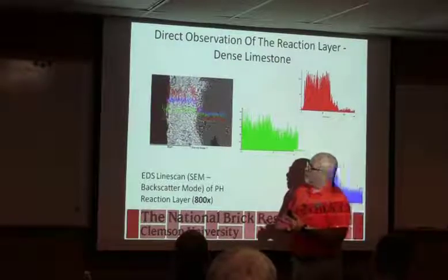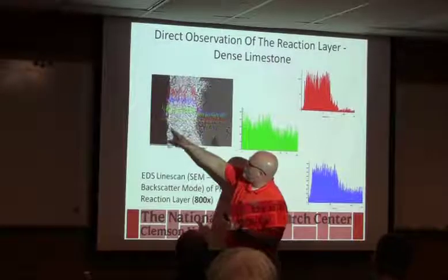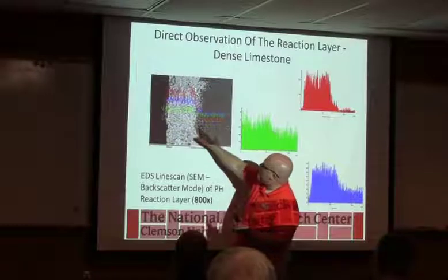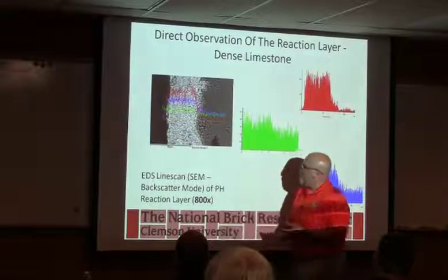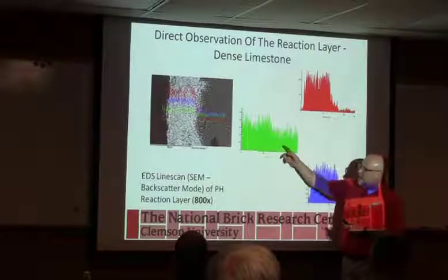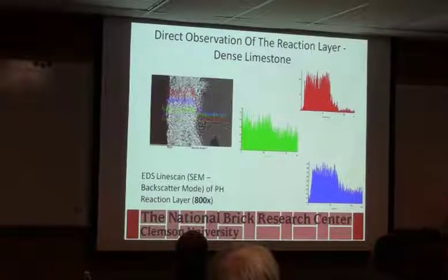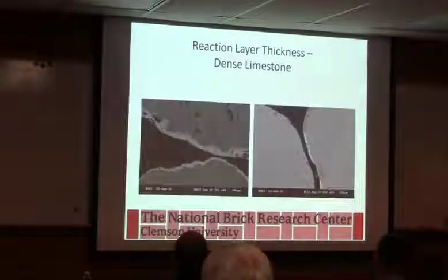It wants the fluorine next, and it'll take the fluorine, but remember, fluorine's small enough that it'll keep penetrating. You can get pretty thick skins on these things with fluorine. And it'll pick up chlorine last, mainly only on fresh surface that the other stuff didn't get. So chlorine's pretty weak in absorption.